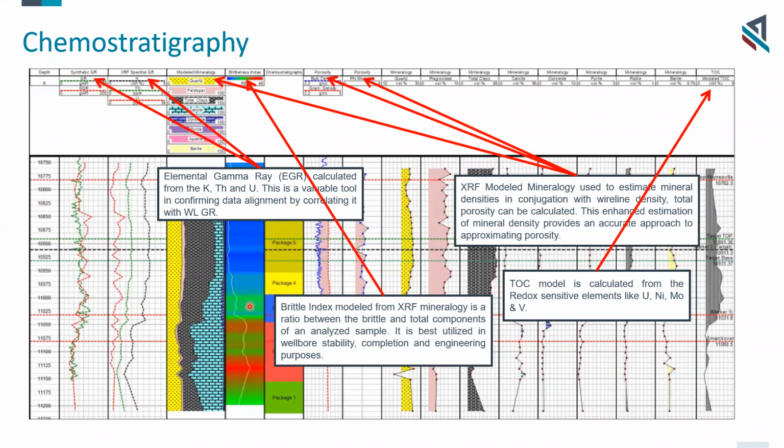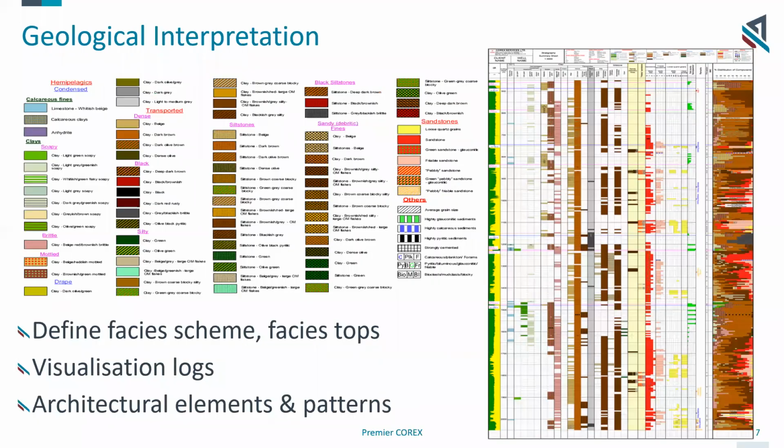So this is a zone, although it's high in total organic carbon, it perhaps won't frack very well because of the ductile clay minerals, which you can see here are high. Further down, we've got an increase in brittleness, so this may frack more easily. It's easier to propagate the frack, and maybe the best zone to pick, although it may not be the highest one of organic content.